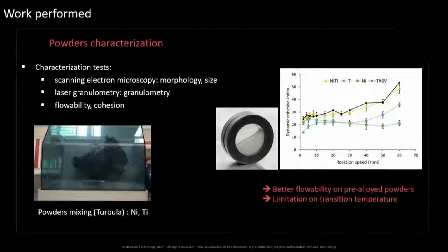So we first tried titanium and nickel separately. We mix the powder. On this small equipment that will mix, but it was very difficult to ensure the homogeneity, and as the transition temperature is given by the chemical composition, it was very difficult to control it.